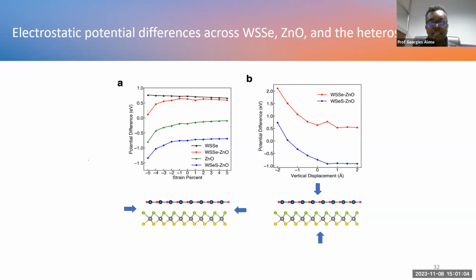But when we apply this strain, we have seen some effects on the dipole moments of the zinc oxide, and we investigated further the effect on the zinc oxide dipole moments. And actually, we learned that if you have a heterostructure, and one of the layers has a dipole moment, you can modulate the dipole moment of that layer and control the heterostructure property. So this is a good way to tune the properties of the heterostructure without any physical contact or something. Yeah. All right, thank you very much.